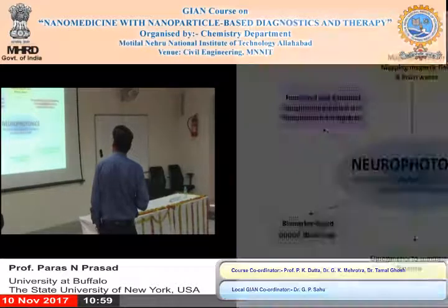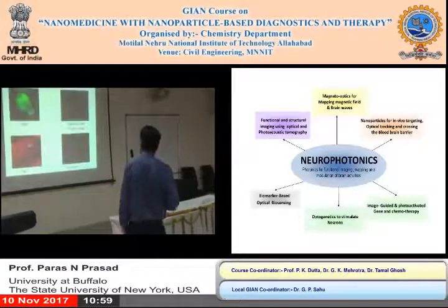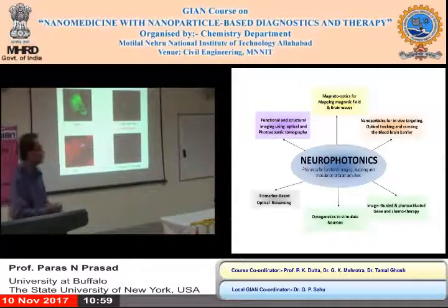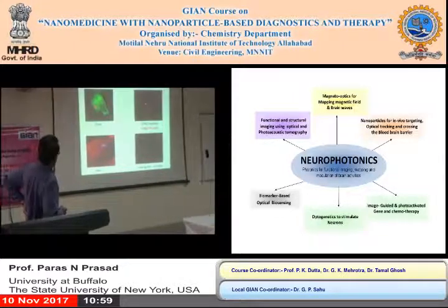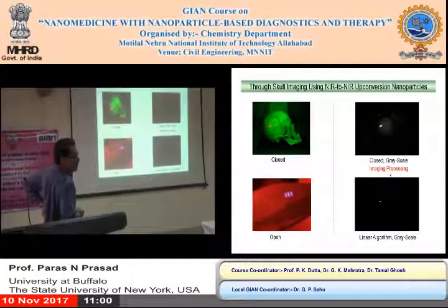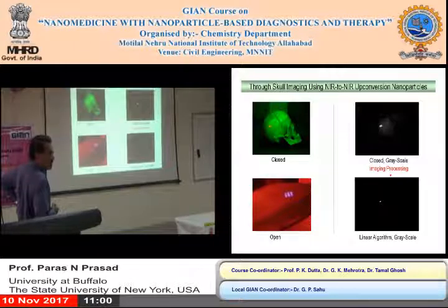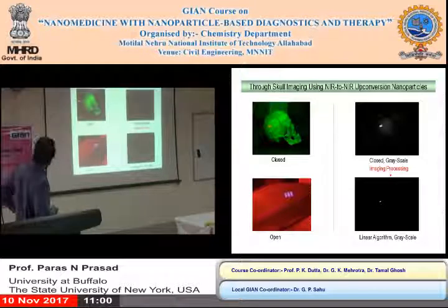Again, you read about neurophotonics, what the scope is. So here, one of them is imaging. We showed that if you use light in the near infrared at 980 nanometers, and your emission is at 800 nanometers, with that conversion that we talked about earlier, you can actually image through the skull. You don't need to make a hole in the skull and use a fiber. You can directly just send the light at 980 and collect it and image it. So that was one thing.